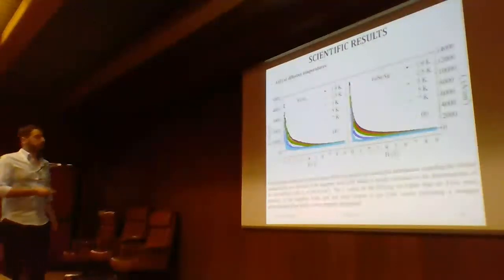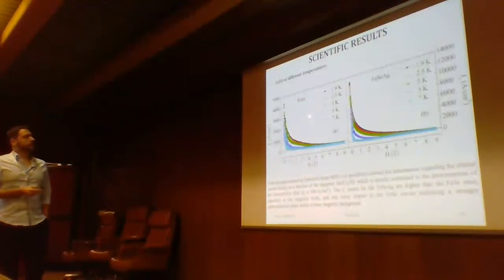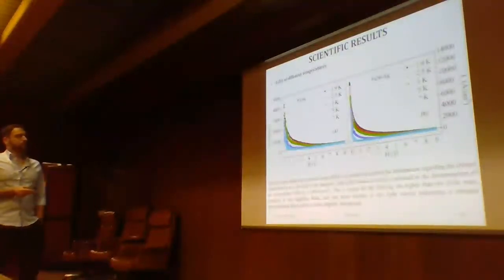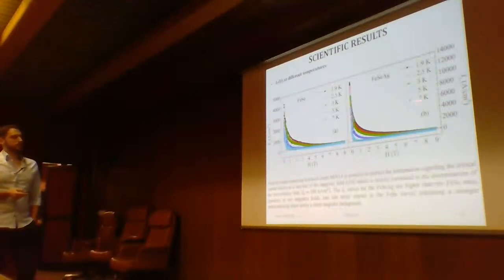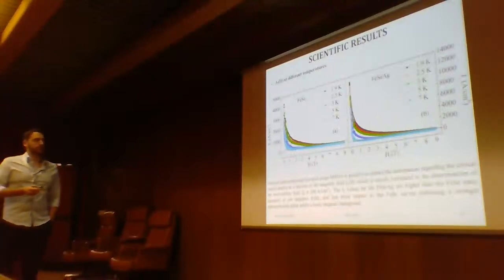inside your material. Now, on the left panel, you can see the iron selenium, and on the right one, the silver doped sample. In particular, observing the scale of the critical current density, we can see that the silver doped sample has a critical current density much higher than the undoped sample, especially at low magnetic field. Between 0 Tesla and 9 Tesla, the signal for the silver doped sample is also less noisy with respect to the undoped sample. And this indicates a stronger superconducting phase and a lower magnetic background in the sample.